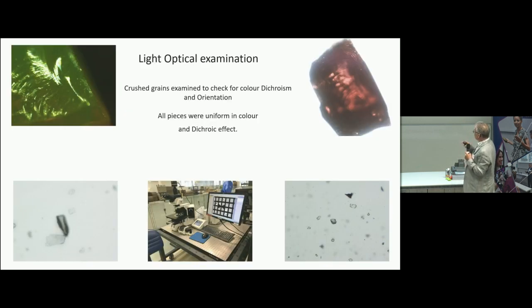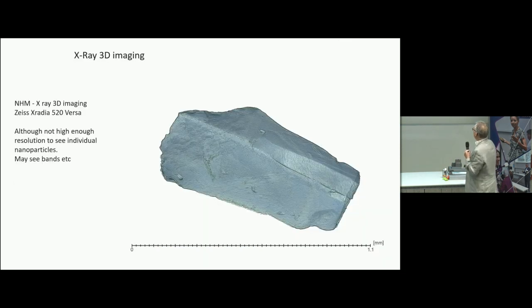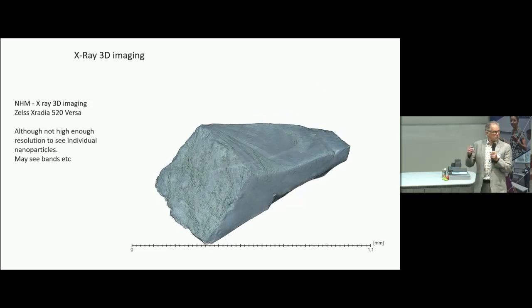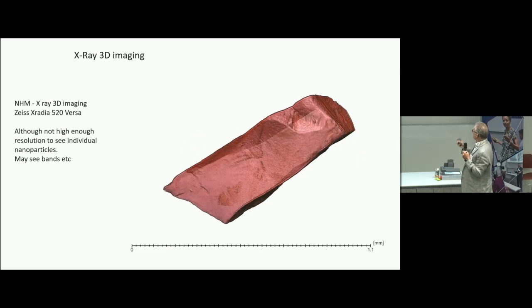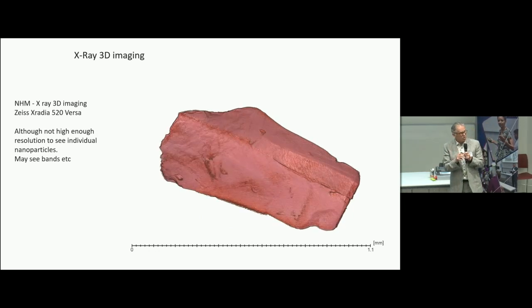I'm going to take you through some of the optical work I did first. I wanted to be sure that anything I looked at had the dichroic property. I looked at hundreds of grains — you can see this one is slightly green in the central part. In the transmission microscope you have to get the beam right through the sample, so you can only look at very small grains, which reduces the probability of finding the gold and silver. I then took a sample to the Natural History Museum's 3D X-ray tomography device. The sample was rotated through 360 degrees, revealing the internal structure; the resolution wasn't good enough to see individual particles, but if there was a layer I'd have seen it. That proved negative.